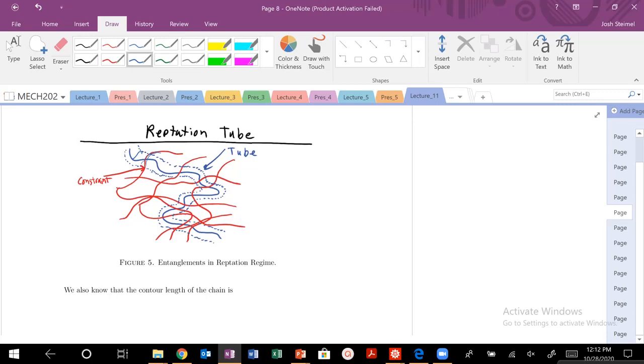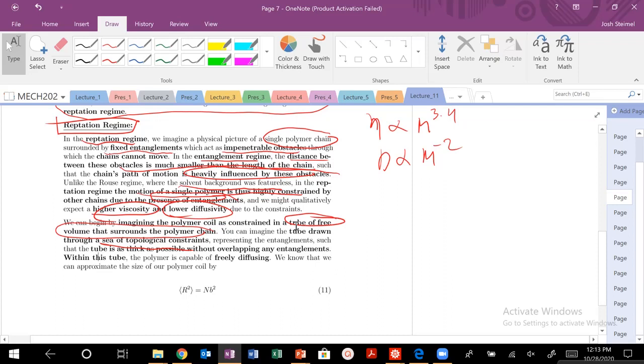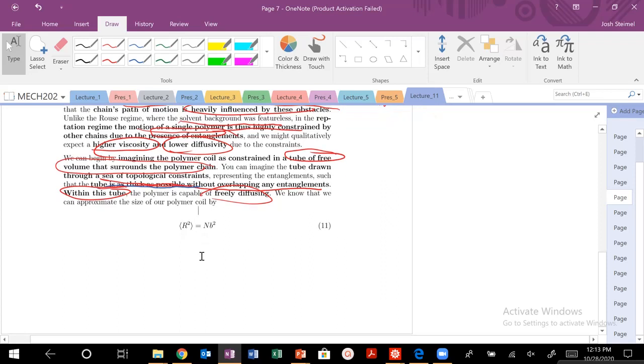We want to draw the tube as big as possible, but it's constrained by the fact that we can't cross into areas occupied by other chains. Inside our tube, we're able to move somewhat freely — our molecule has some free volume. Inside this tube, our polymer can freely diffuse essentially in one dimension. The size of the tube depends on the amount of free volume that polymer can access, which changes depending on the number of those topological constraints.